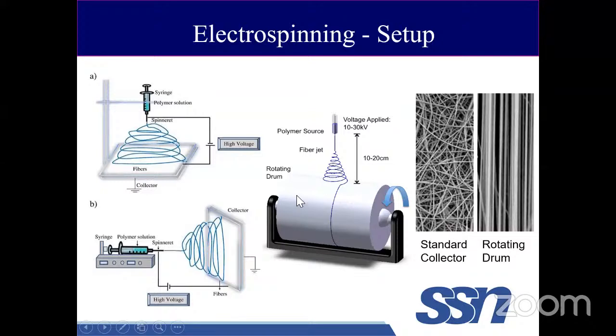In a drum collector, we can vary the RPM of the drum collector from about 100 to 1500 RPM, right? This image will clearly give you an idea how the alignment of these fibers changes when we use different types of collectors. When we use standard collectors, we have misaligned fibers, whereas when we use drum collectors, we will have aligned fibers, as well as reduced fiber size when we go with rotating drum collectors, right?